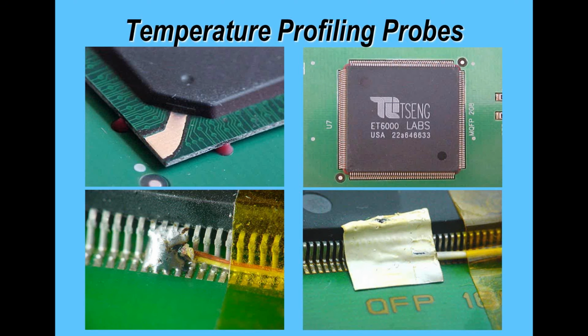And the two examples at the bottom here, I show thermocouples which have been soldered to leads, and I've soldered to 2 or 3 leads in this particular case, and the bead of the thermocouple is within the solder. People may argue there might be a difference in a couple of degrees Celsius between those solder joints where I've put a little bit more solder on, but that thermocouple is not going to come off and I'm still going to get pretty accurate readings.